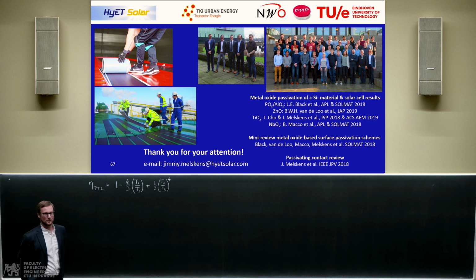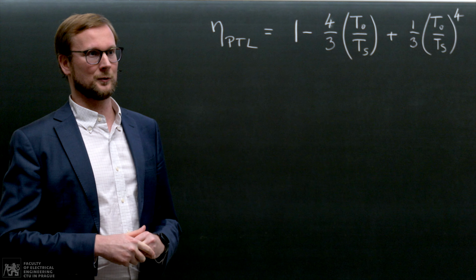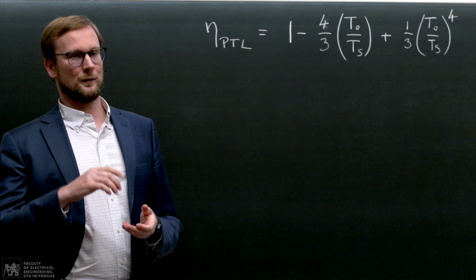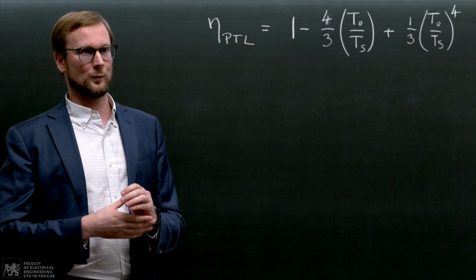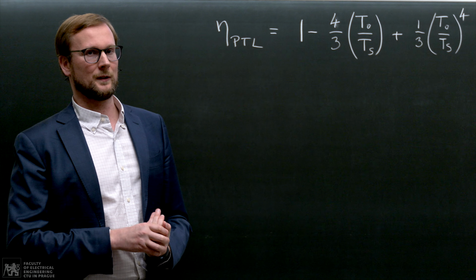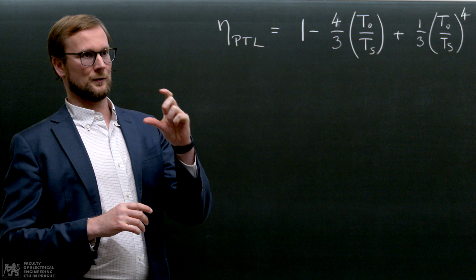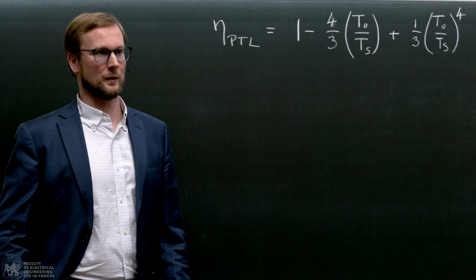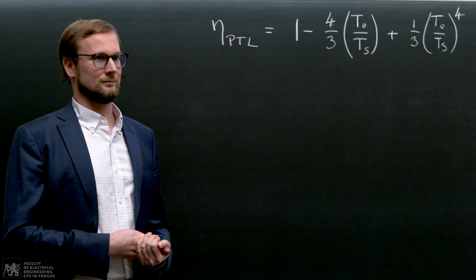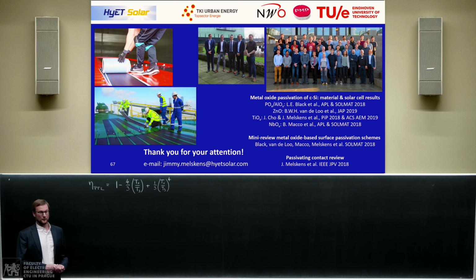Yeah, that's a good question. So the answer is that you need to have a layer that's very thin because it's dielectric. There's an argument in the community about whether the transport through this layer is tunneling, or defect assisted transport. You cannot go beyond, let's say, 2 nanometers if it's a very thin layer. If it's grown in another way, where we have some holes in the material, maybe 4 nanometers is initially okay. But it is slightly more electron selective because of differences in band offsets. So it has a slight preference for that. But it can be used in both electron and hole selective contacts.